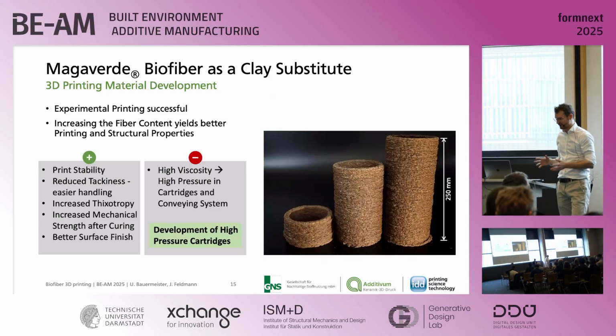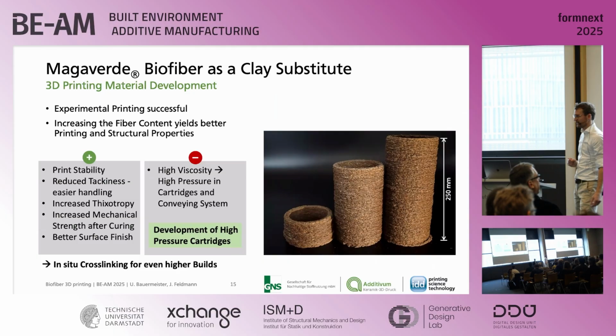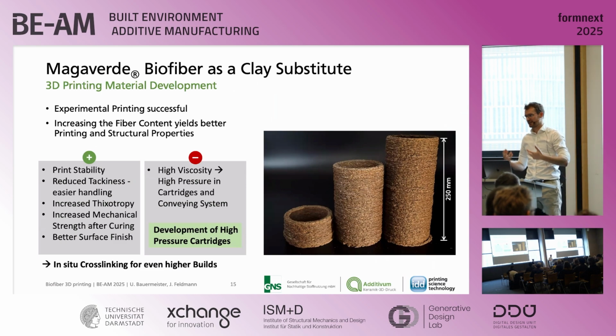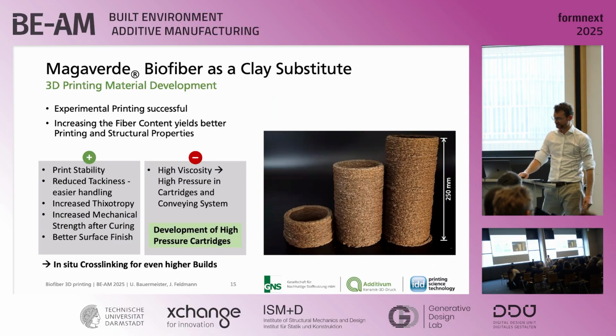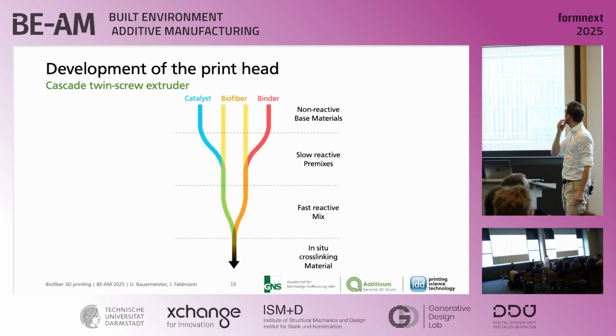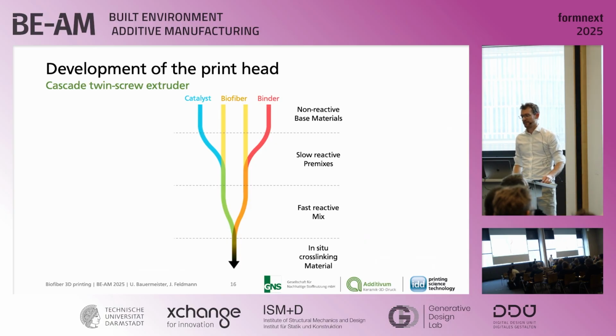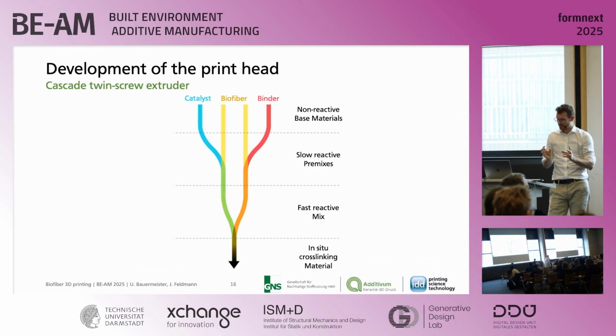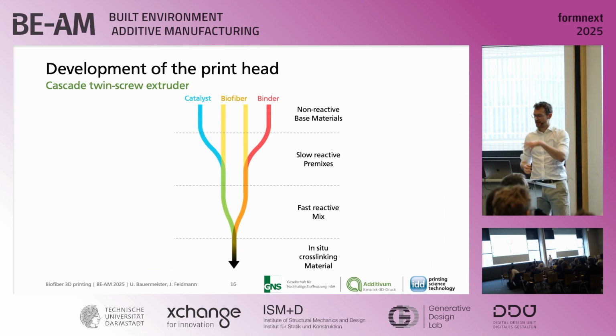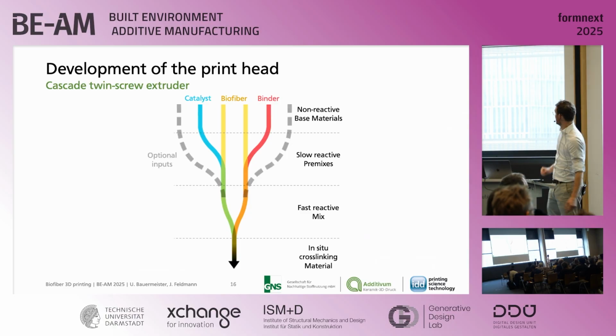Another thing we want to take care of, because we want to build really large parts such as these insulation panels, is to look into having the cross-linking of the binders happening between the fibers right after printing. So we want that once it's placed on the part or on the build platform, it starts cross-linking there already. It won't get completely hard, but at least becomes a little more viscous, a little firmer, so that it doesn't collapse under its own weight. To do so, we thought of basically a mixing extruder, where we can have the catalyst and the biofiber and binder pre-mixed, and then mix it right before we push it through the nozzle, so that it already starts solidifying right after printing on the part. And it would be really awesome if you could add more additives, such as dyes and others as needed.